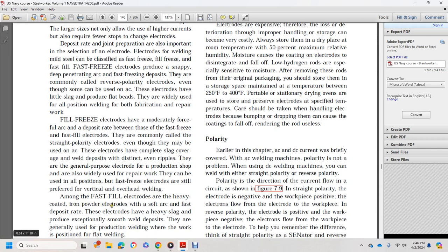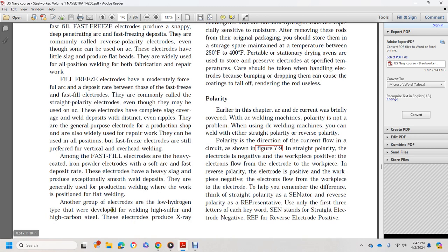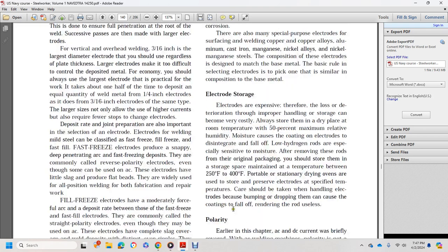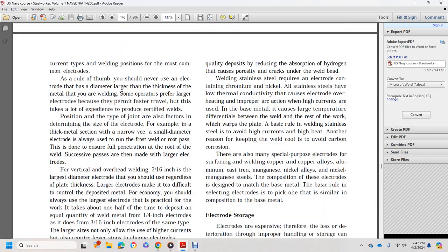Among fast fill electrodes are the heavily coated iron powder electrodes, which offer a soft arc and a fast deposit rate. These electrodes have a heavy slag and produce an exceptionally smooth weld deposit. They are generally used for production welding, where they work best in the flat position. Another group of electrodes, the low hydrogen type, is developed for welding high sulfur, high carbon steel. These electrodes produce X-ray quality deposits by reducing the absorption of hydrogen, which causes porosity and cracks under the weld bead.